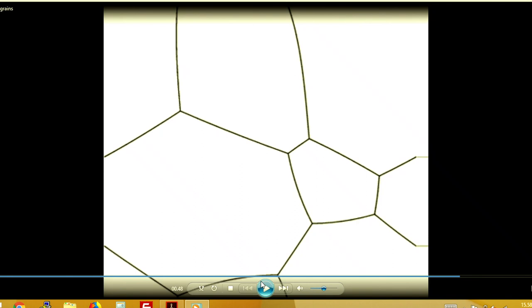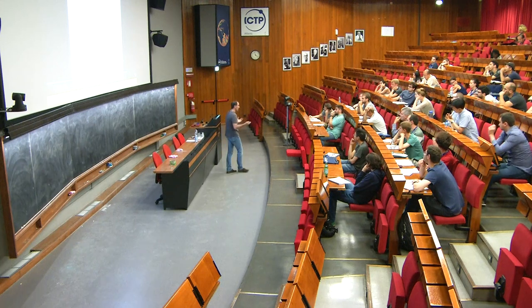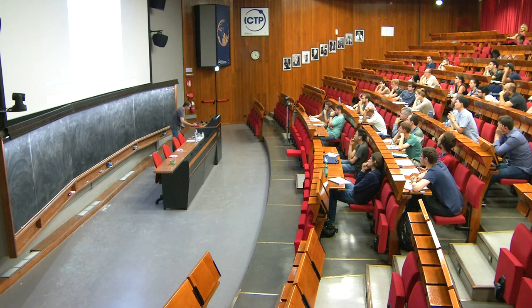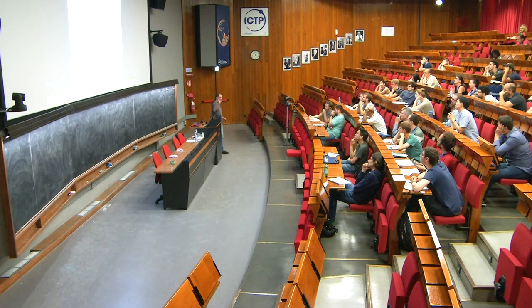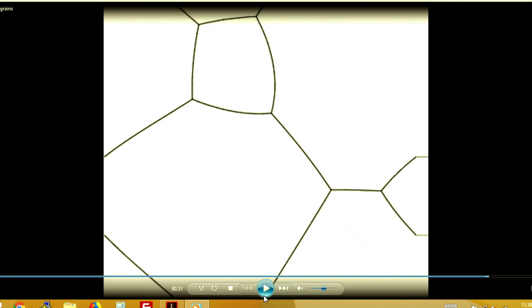All the triple junctions, if you look, always have the same three angles of 120 degrees between the three curves concurring at the triple junction. So you have these special times when something happens — when you can see four-points or five-points — and the region has collapsed or a curve has disappeared. In all other times, you only have triple junctions with 120 degrees. I hope it's going to happen what I was saying, that this curve is disappearing. Here it is. There was no collapse of a region — one curve disappearing and an opening in the other direction with two other triple junctions going more or less orthogonally.